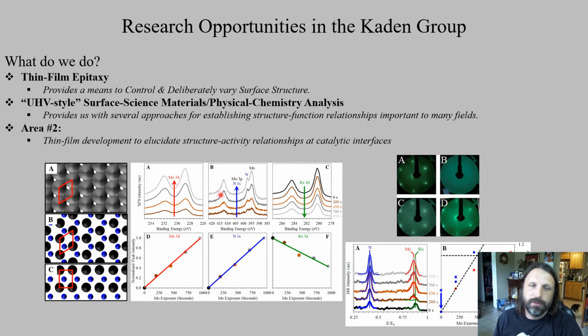So we use X-ray photoelectron spectroscopy, which is a very useful tool that we use a lot. We use that to tell how much of a different element is present at the surface of something. We use that to tell what kind of chemical state those things are in. So for example, here you've got molybdenum and nitrogen. Where these peaks show up exactly, meaning the little bit of shift left or right, gives you information about whether or not that thing is oxidized or reduced, chemically speaking. The amounts then tell you how much of each, and you can put both together, then get an idea of stoichiometrically what kind of compound you have. In this case, it was the molybdenum nitride, MoN, we were trying to make.